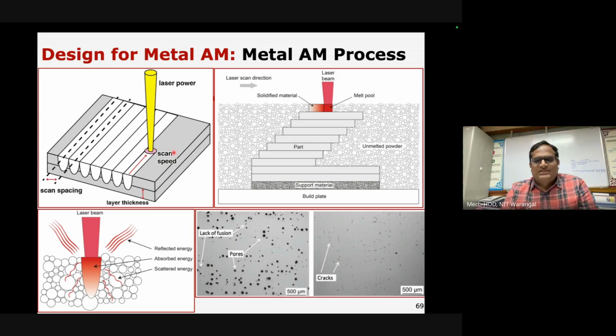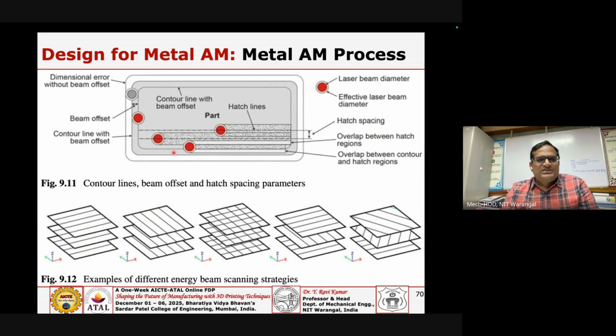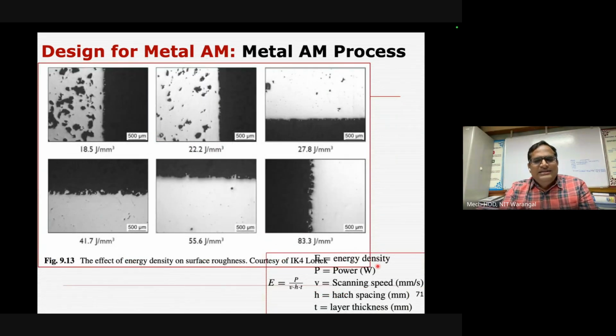Maybe by adjusting some process parameters, you can play with some of the parameters, or you can even change the scanning strategies in order to distribute your residual stresses. Basically, that is a major challenge which we need to handle. And energy density, once you model this, we need to understand the energy density. It should not be too low and should not be too high. Then we need to optimize this energy density, which is a function of laser power, scan speed, hatch space and layer thickness. So this is the kind of relation that we need to understand.